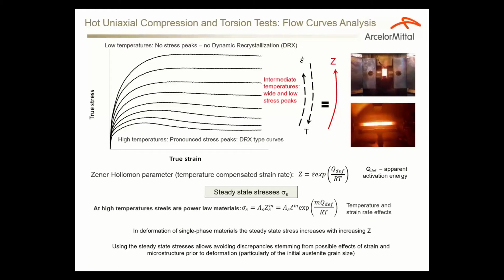In our way of translating the test results into mill language, most of the time we use steady state stresses, because they can give us an idea of what is going on with microstructure. It's a better idea than if we use strain dependence or dependence on the initial microstructure. Once we establish the dependencies for steady state stresses, we can go deeper and analyze what's happening at small strains or how the initial microstructure affects this.